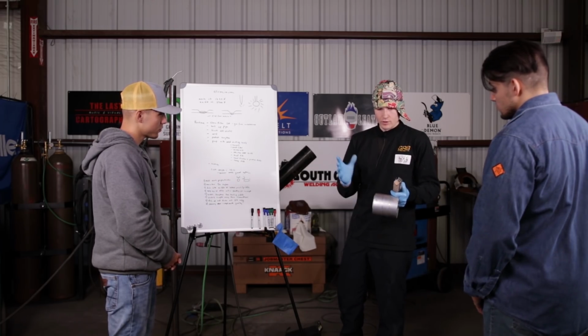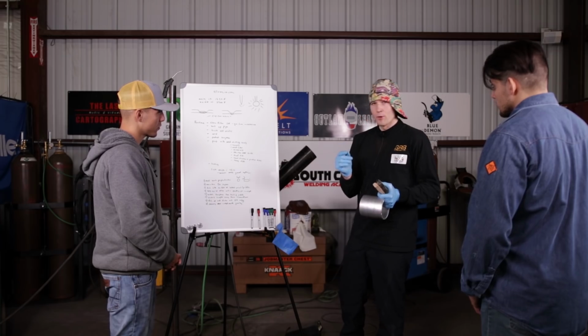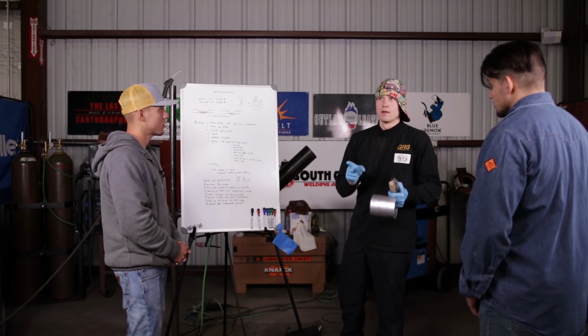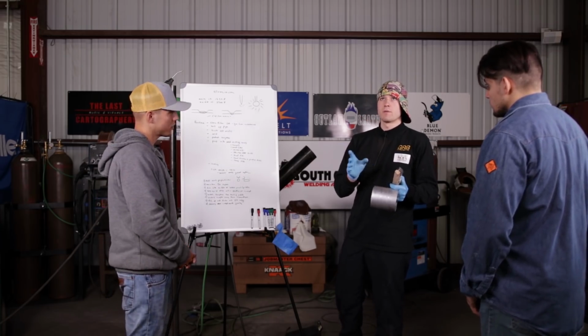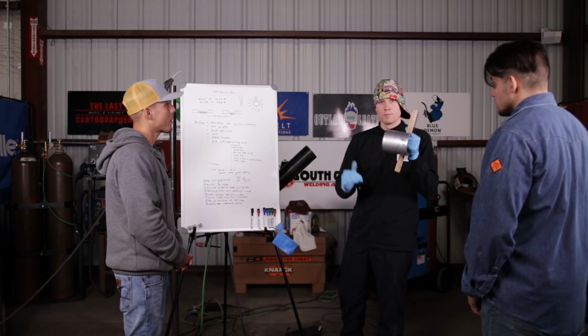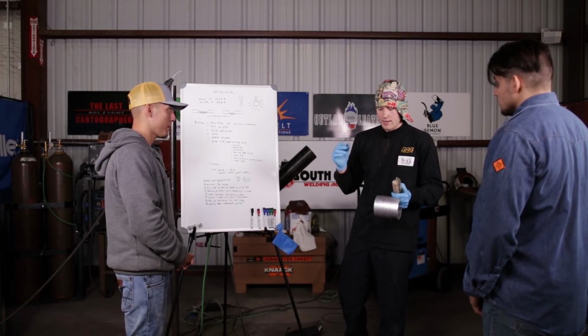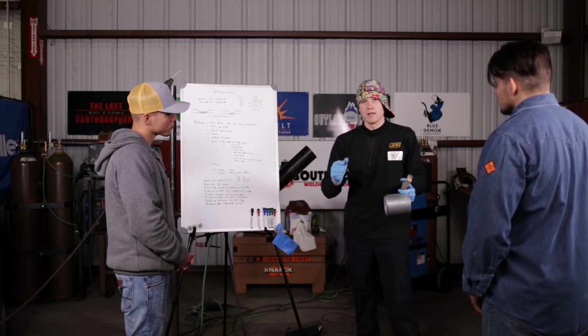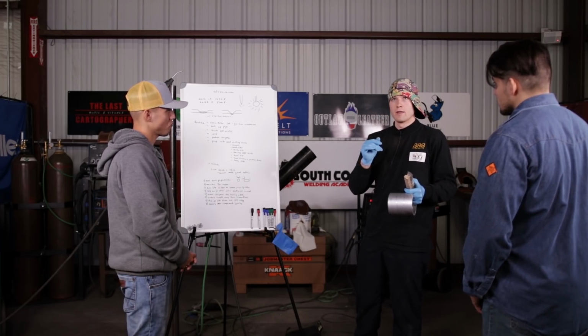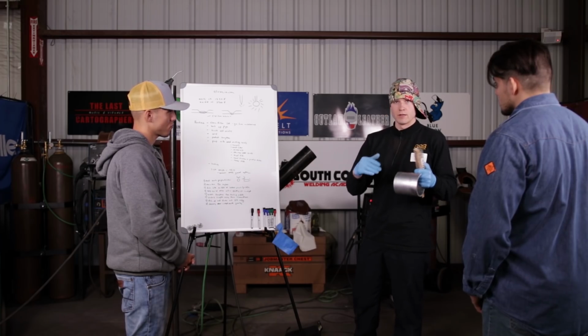it doesn't matter relatively what machine. You can still do the welding as long as it's AC. For frequency, I'll be running probably about 120 to 160 hertz. For balance, maybe about 65, which is the balance of the positive and the negative. On the Miller Dynasty 350, we can independently change the electrode positive side and the electrode negative side, which is the cleaning action and the welding action. We can also change different waveforms in the secret menu. You just hit the average button and the dig button, and you can change through all the settings and waveforms. I believe there's a sine wave, triangular wave, advanced square wave, and soft square wave.